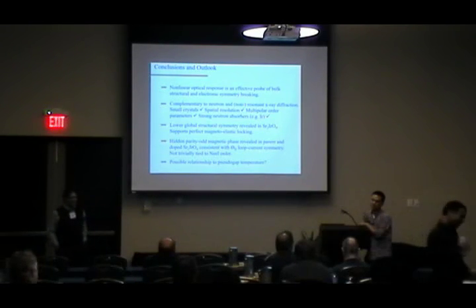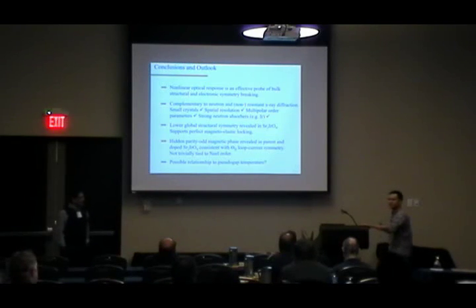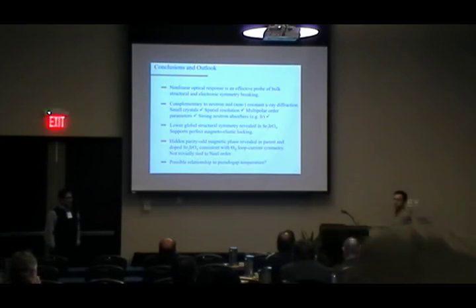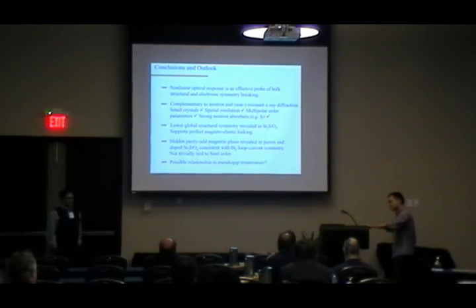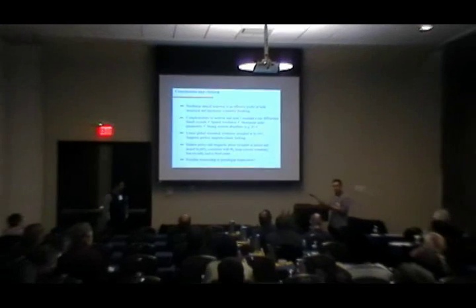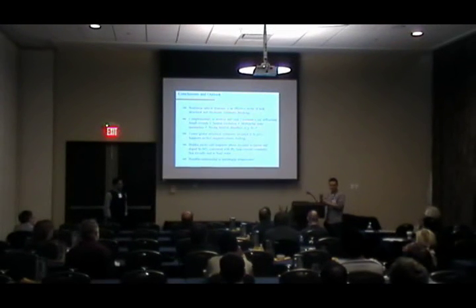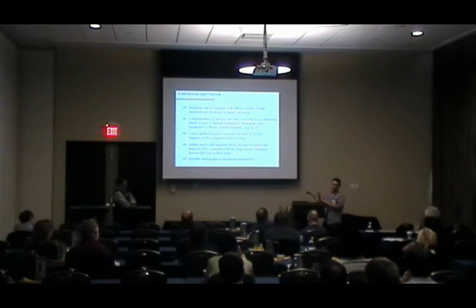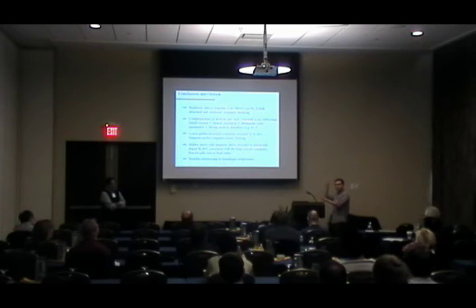Questions? Why can't you directly measure the transport properties, in the context of superconductivity? Right. So with bulk doping, there's a saturation that's actually pretty small. At least for these lanthanum and rhodium species, which they've been using to dope, you can't stuff so much in. It saturates at about, I forget, 6-7%. So the samples on which the d-wave gap has been found are surface doped. They cleave it in vacuum and dose potassium on it. And the doping level is far larger in those cases. So whatever they're seeing in photoemission is only happening on the surface first.